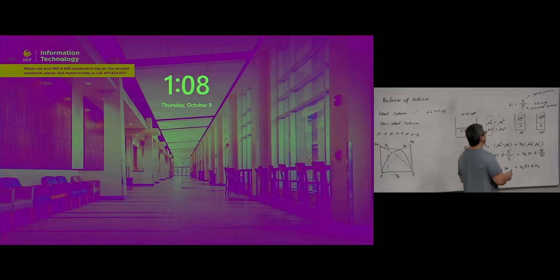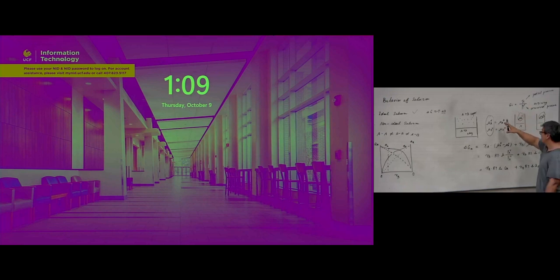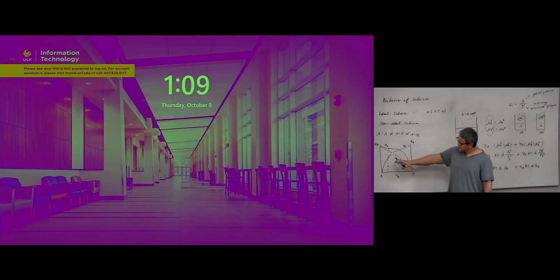Again, the activity definition is the partial pressure of the i component generated from the alloy compared with the saturated pressure generated by the pure element. Okay? Got my point? That's the activity. If the solution is ideal, the partial pressure divided by the total pressure simply equals the molar fraction, right? But if we consider the repulsive interaction, if the two molecules are repelling each other, the partial pressure goes up. If they are attracting each other, the partial pressure goes down. That's the reason for the repulsive interaction: the activity is higher than the molar ratio. And for the attractive interaction, the activity is lower than the molar ratio. Okay? Make sense?